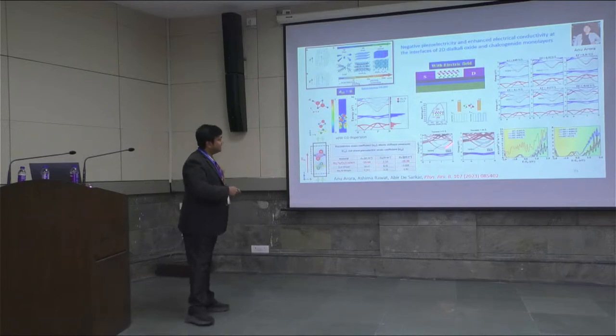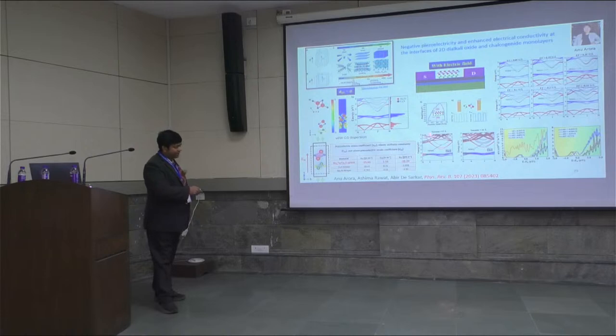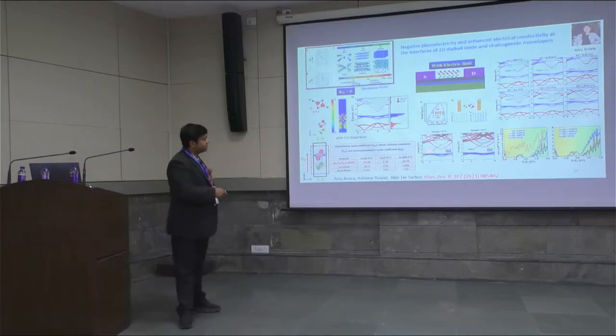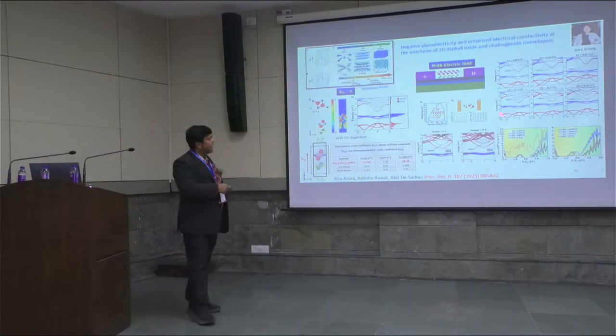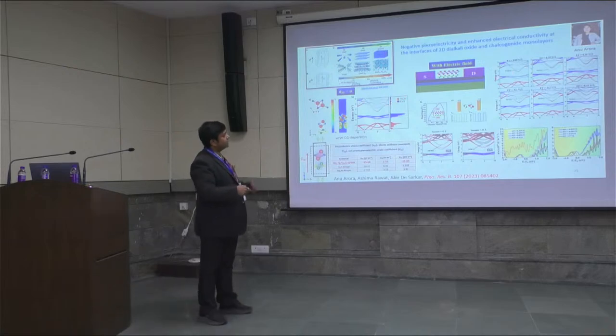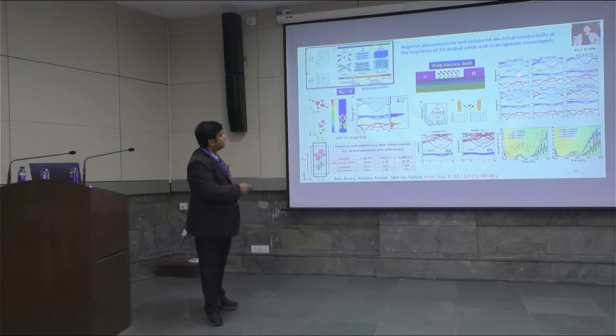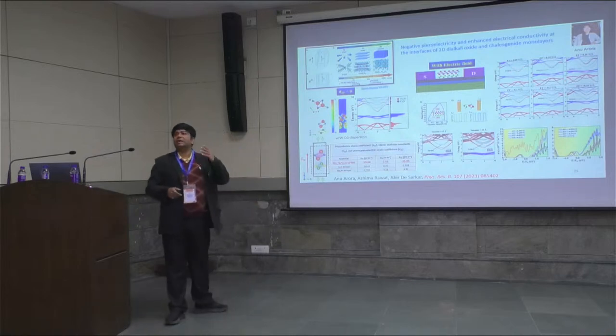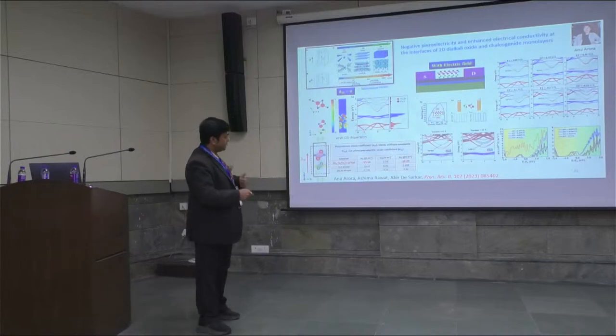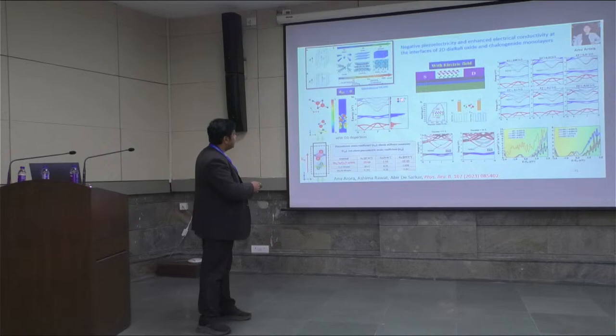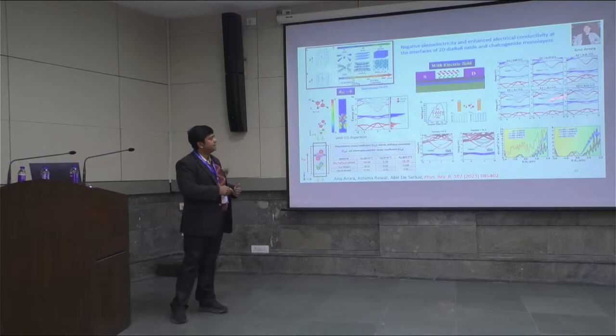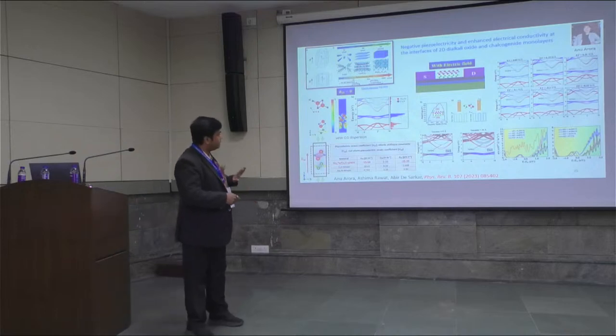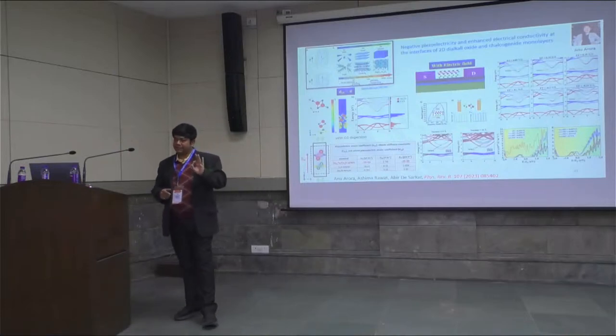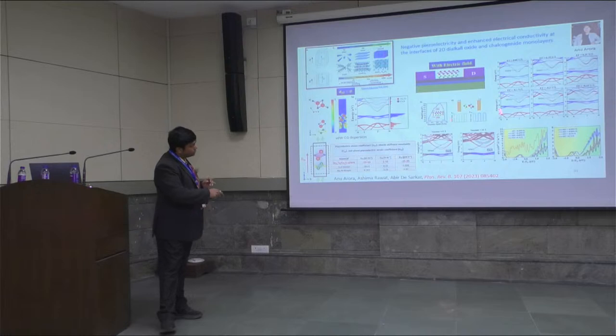And these monolayers show a nearly free electron gas state having a parabolic dispersion similar to that of graphene. This arises from the image potential surface states as in graphene. And in this van der Waals hetero bilayer, when the electric field is applied along plus z or minus z direction, these NFE states reach the Fermi level and enhance the electrical conductivity. When a positive electric field is applied along the plus z direction, the red bands move upward relative to the blue bands. And when a negative electric field is applied, the band movement is opposite. And now this closing and opening of the band gap in the presence and absence of electric field can be utilized in digital electronics.